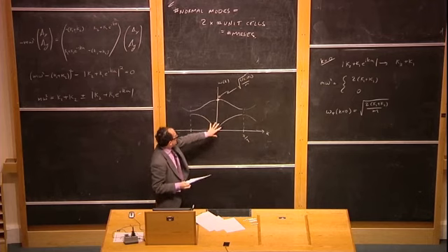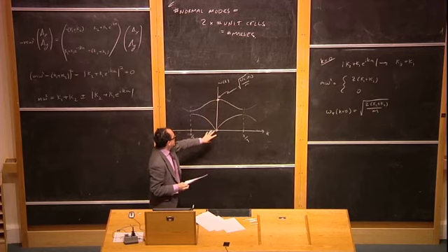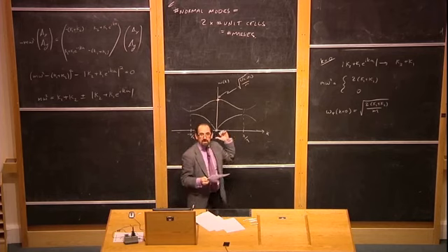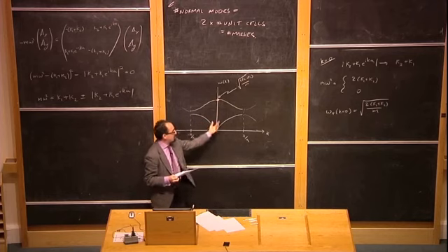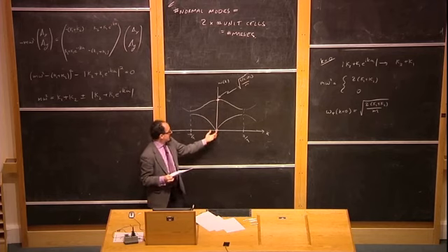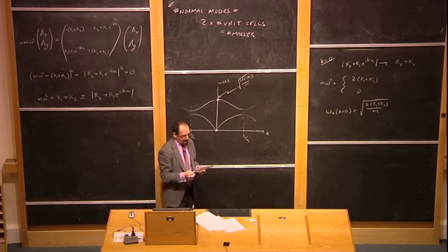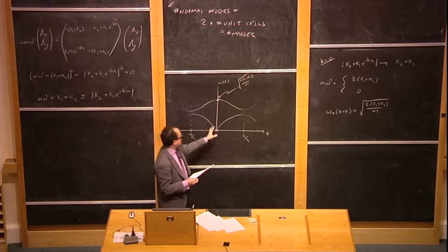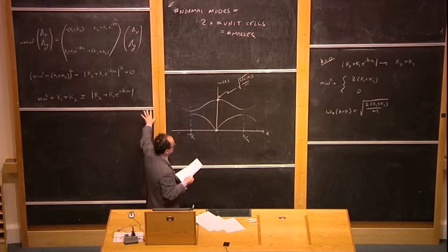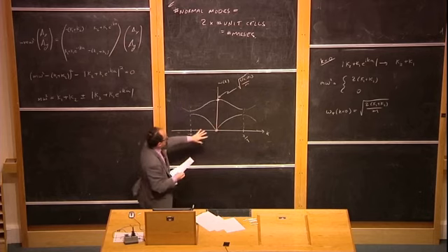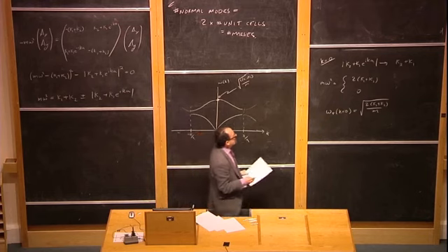And so we have the low energy mode and we have the high energy mode. Now, we'll come back to the high energy mode in a moment, but the low frequency mode is one that we should expect to be there, because there should be sound waves somewhere in this system. And sound waves should have a spectrum with frequency linear in wave vector, coming down to 0 at 0 wave vector. To convince ourselves that that's what's going on with this equation, we have to do a little more math and expand the dispersion curve near k equals 0. So let's see how we do that.